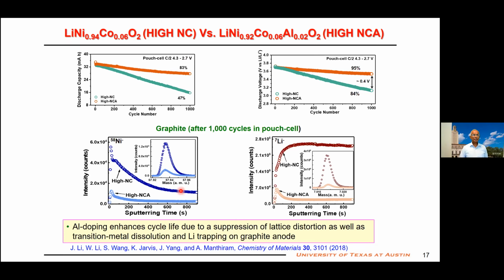Now let's take the graphite anode paired with this cathode and that cathode, like I talked about in the previous slide, using time-of-flight secondary ion mass spectrometry. You can see on the graphite anode, you have less nickel if you have 2% aluminum in the cathode, and you have less lithium trapped on the graphite anode if you have 2% aluminum.